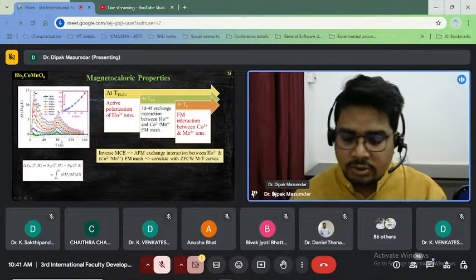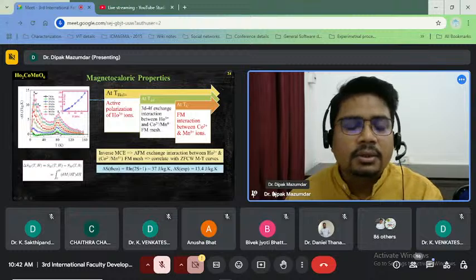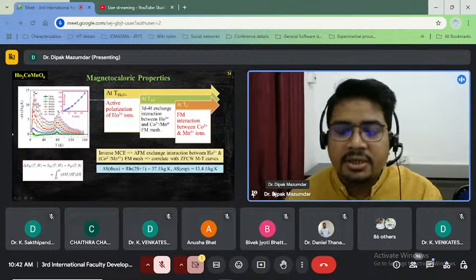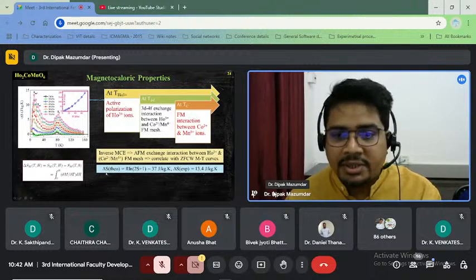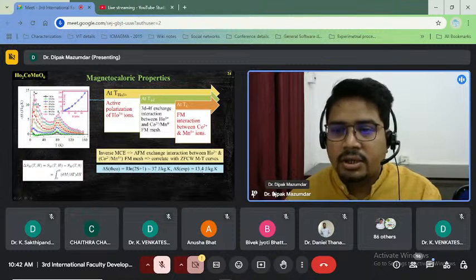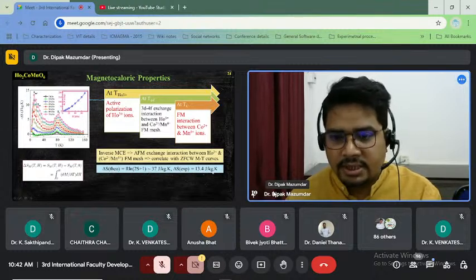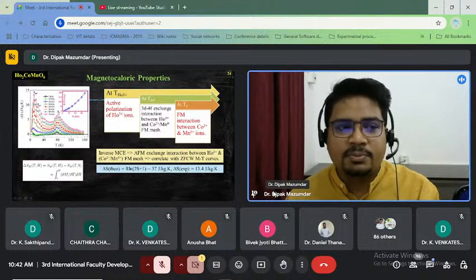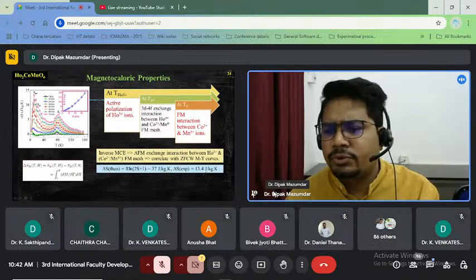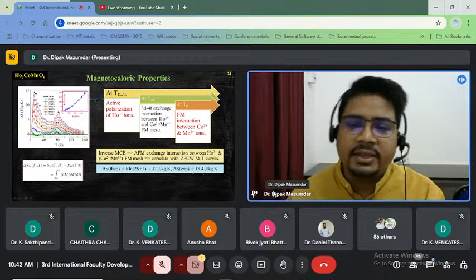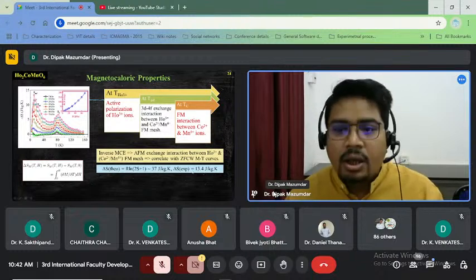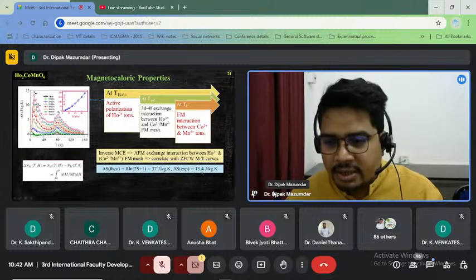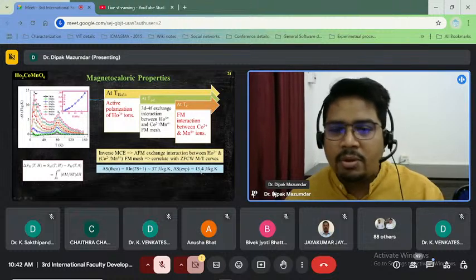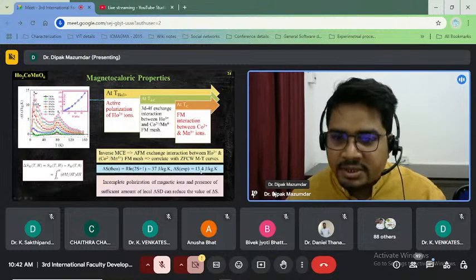And we have also estimated the theoretical value of entropy change by using this formula, which is 37 joule per kg Kelvin, but our experimental data comes to around 13.4 joule per kg Kelvin. So if everything is perfect, everything is okay, then why does this value come out very low? There will be different possible reasons.